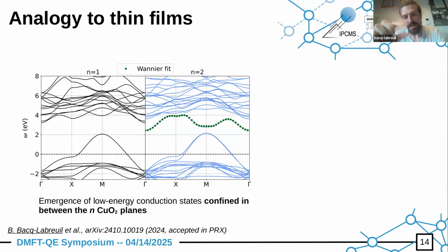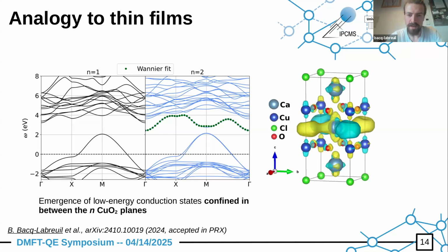Because this band is isolated, we can perform a Wannier fit to get an intuition about the physics of this conduction state. And the Wannier orbital that we see is this one. It's a very spread-out orbital in the interstitial region between the copper-oxygen planes. This tells you why it does not exist in the n=1, because this state needs at least two consecutive copper-oxygen planes to be able to live in between them. So this is really a state that is confined between the copper-oxygen planes.